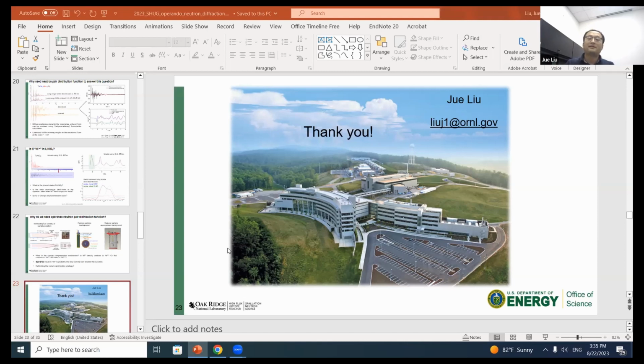So I think if, for the carbon additives, we can get rid of the hydrogen, that will be enough. Then we can quantitatively subtract the background. The real challenge I see at the moment is really the separator, which is very difficult to deuterate at the moment. That's what I have, because it's still an ongoing project. I hope that we will have something to share with you in the next 1 or 2 years, for the operando PDF.